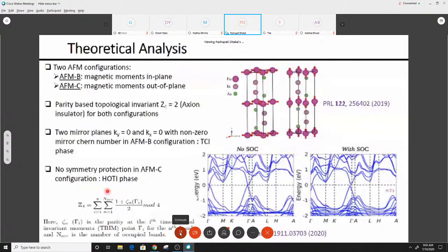Our theoretical analysis showed that there are two mirror planes, ky equals 0 and kx equals 0, with non-zero mirror Chern number in the AFM-B configuration, and they protect a gapless topological state. Therefore, in the AFM-B phase, EuIn2As2 is a topological crystalline insulator. However, in the AFM-C configuration, there is no symmetry protection and the surfaces are gapped out, and the EuIn2As2 system realizes a HOTI phase with Z4 equals 2.